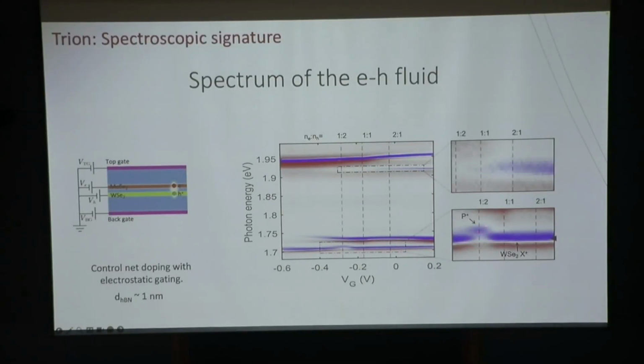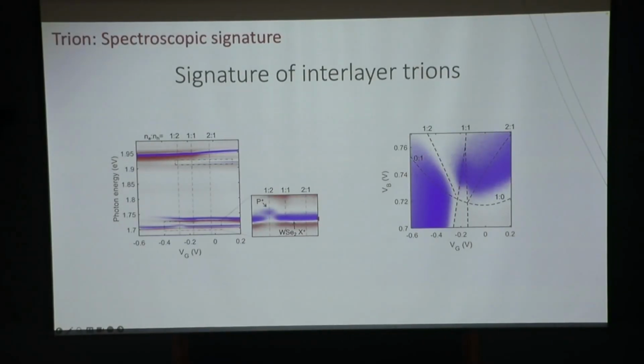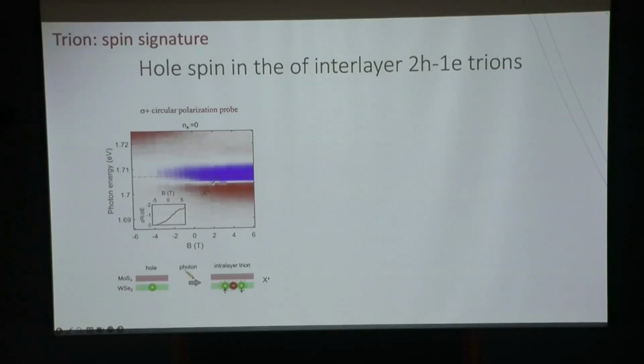So why does this happen? First I want to show this is actually a signature of the trion by looking at this feature across the whole phase diagram. What you can see is that this feature is very well correlated with the 1 to 2 doping line. So that means it's not just a coincidence at some particular density. Across the whole density range, at the 1 to 2 ratio, this spectral feature is there. But to further convince us this is a real trion, we can look at its spin behavior.